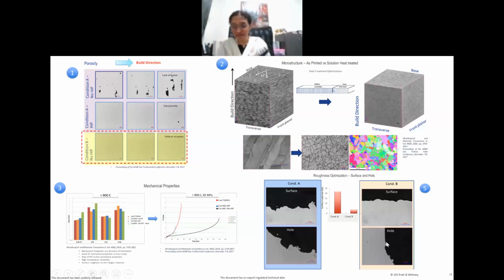So what we did very cleverly in this particular example, and it can't be generic across all designs, all products, all cooling hole dimensions, we quickly changed the additive manufacturing diameter of the hole slightly larger in that particular customer product, and we calculated what is the pressure drop across that particular diameter. And the beauty of additive manufacturing is overnight you can change the design and 3D print it without having to go to a casting pattern, and then having the pattern qualified and then making a part. That's why this is so beautiful and it's so fast. So that's what we did, but definitely it's a challenge to watch out for, especially if you're working on actual product development.